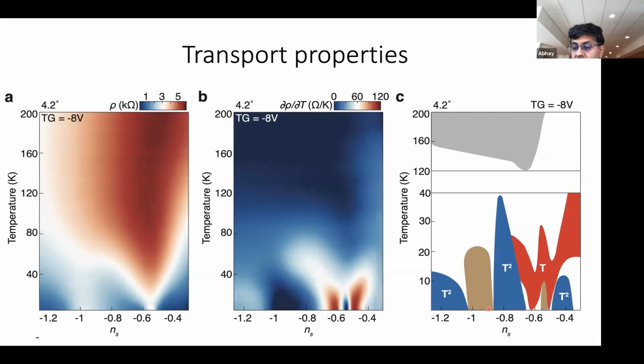So this phase diagram shows what the different types of behavior are observed. And you see something very reminiscent of quantum critical behavior. You see a region of T² behavior far away from this point, and this point is where T-linear behavior extends all the way down to T = 0. Then here there's a metal to insulator transition, once again a region of T-linear behavior, and to the right of that, T² behavior emerges again. This T-linear behavior goes out in a very suggestive fan-like looking object. If I sit at this doping and raise the temperature, initially it's T², but as I raise the temperature it goes over into T-linear before eventually going to saturation at high temperature.